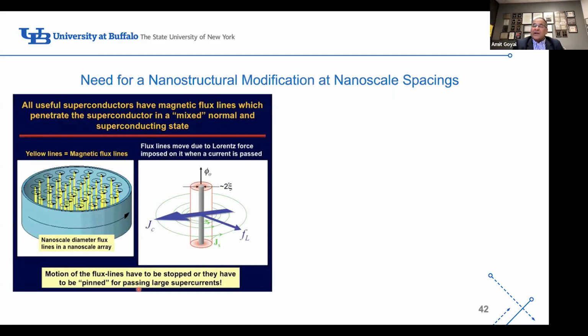Once we made these wires in kilometer-long lengths, we thought our work was done. But it turns out it wasn't. Why? All high-temperature superconductors, useful superconductors, are called type 2 superconductors. They resemble Swiss cheese. Swiss cheese has holes in it. And type 2 superconductors have magnetic flux lines which go through the superconductor, in yellow. If I take one of these yellow lines out and put it here and pass a current in one direction, then there's a Lorentz force in the perpendicular direction which moves this magnetic flux line in this way. If it moves, it destroys superconductivity and creates resistance.